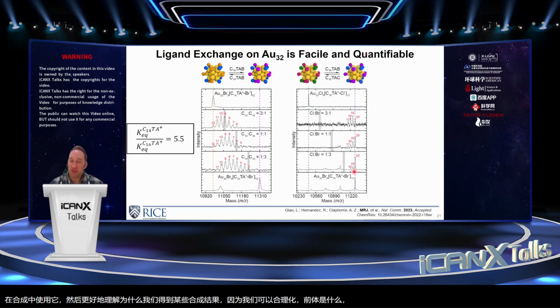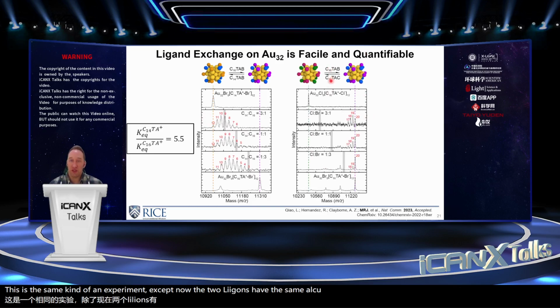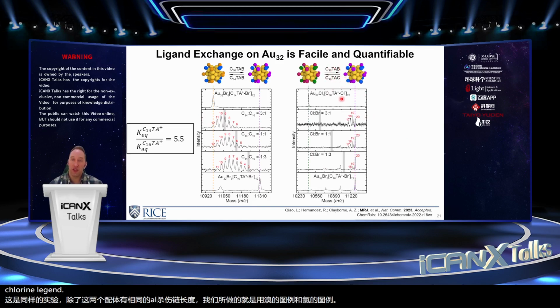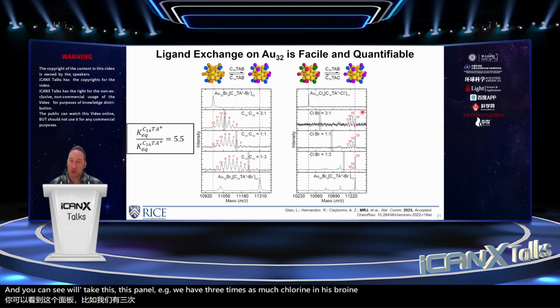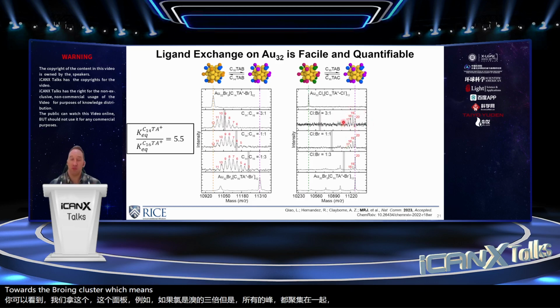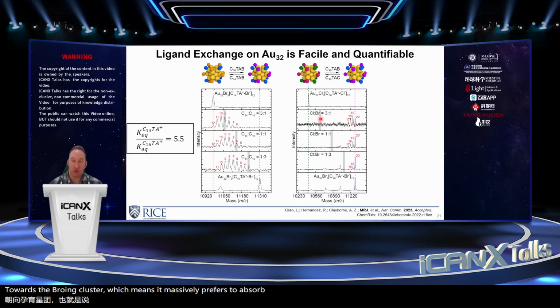This is the same kind of experiment, except now the 2 ligands have the same alkyl chain length, and all we're doing is using a bromine ligand versus a chlorine ligand. And you can see, we'll take this panel, for example, we have 3 times as much chlorine as bromine, but all of the peaks are clustered towards the bromine cluster, which means it massively prefers to absorb bromine over chlorine.